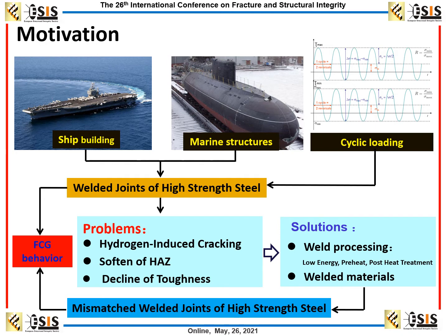We can do it from two aspects. One is to solve the problem by the welding processing, just like lowering the energy, preheating the welded plate, or doing the post heat treatment after the welding. Another way is to use different welding materials. From this way, we can obtain the mismatched welded joint of a high-strength steel.